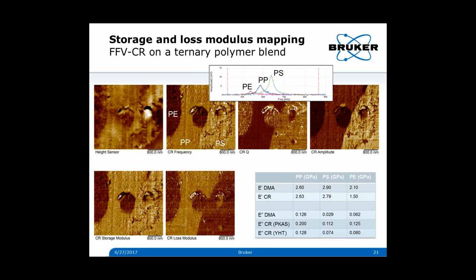These have been time temperature superposed up to the frequency of the contact resonance. Then you actually get very, very close agreement with the polypropylene, polystyrene, and reasonable agreement with polyethylene also for the storage modulus. For the loss modulus, the agreement is not as good, and essentially the first method is off by about a factor of 2, roughly, for the polypropylene and the polyethylene, and a little bit more for the polystyrene. The second method is better. It's using the polypropylene as an internal reference, so that one is going to agree, but also the other numbers are a bit better. But still, there is definitely room for improvement in that loss modulus calculation.